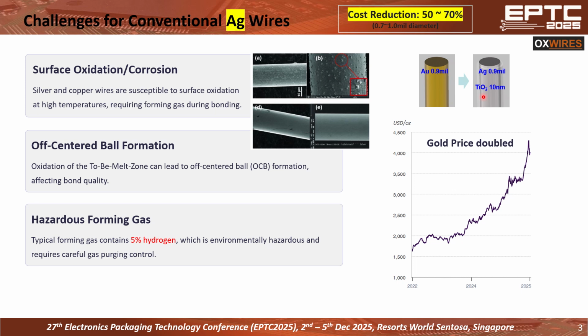Then we have to know about the shortcomings of conventional silver wire. Shortcoming number one is the surface oxidation and corrosion. Silver and copper wires are susceptible to surface oxidation and corrosion. So it requires a use of forming gas during wire bonding operation. Without a forming gas, you're going to get off-centered ball formation. Off-centered ball doesn't allow a good bondability. On top of that, forming gas is a dangerous gas because it contains 5% hydrogen gas, so the wire bonding assembly people do not want to make use of a forming gas.